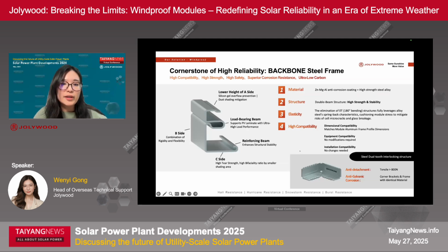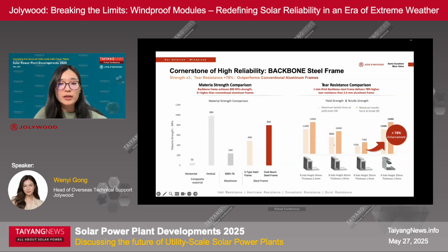The material strength is about 3 times higher than the conventional aluminum frame, and the tear resistance can be enhanced by more than 78%.